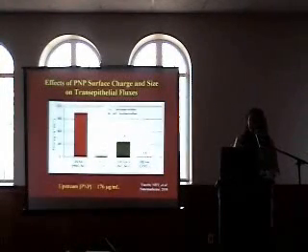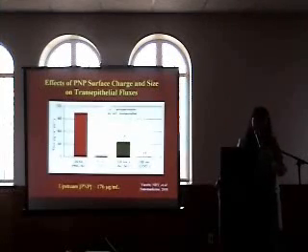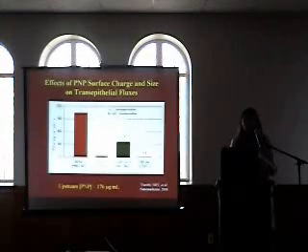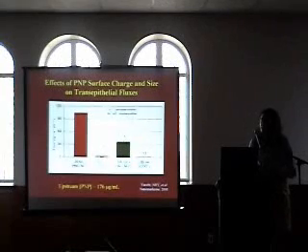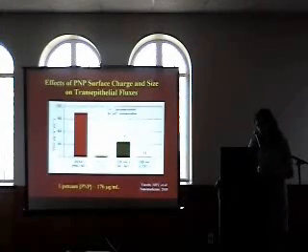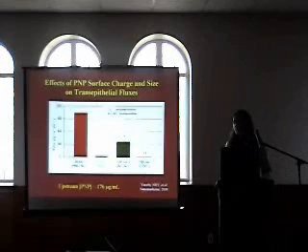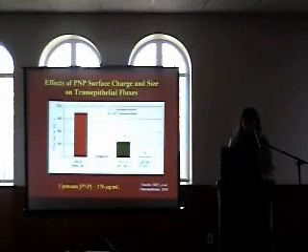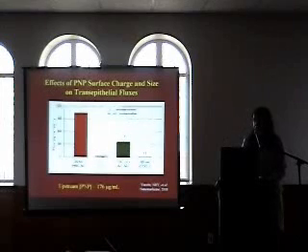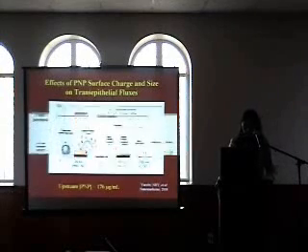This is not a new slide, but it's the starting point of this research and was really exciting for us. It's already published in Nanomedicine. What we observed was that not only do these nanoparticles translocate across alveolar epithelial cell monolayers, but positively charged particles also transport 30 times faster than negatively charged particles when they have a similar size. As for size, the smaller particles go 3 times faster than bigger particles when they have a similar surface characteristic, indicating that the trafficking rates of these particles strongly depend on their charge and to some degree on their size.